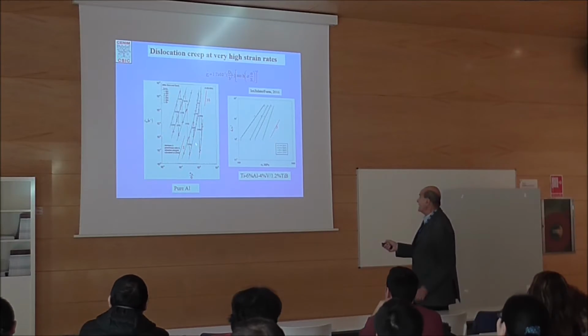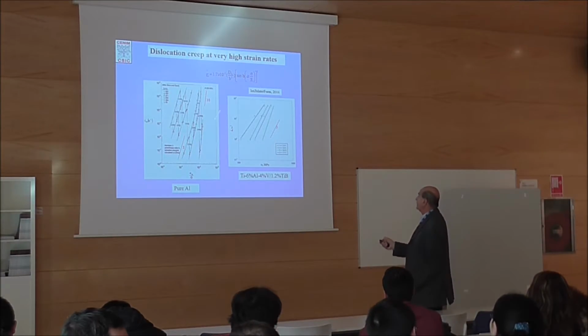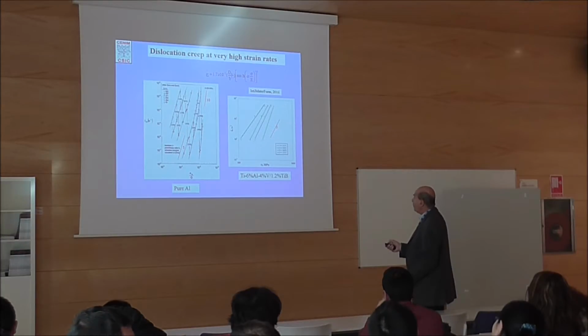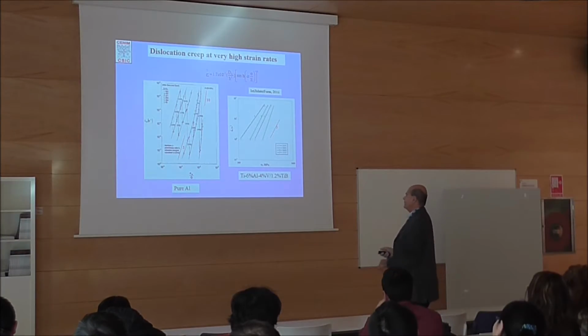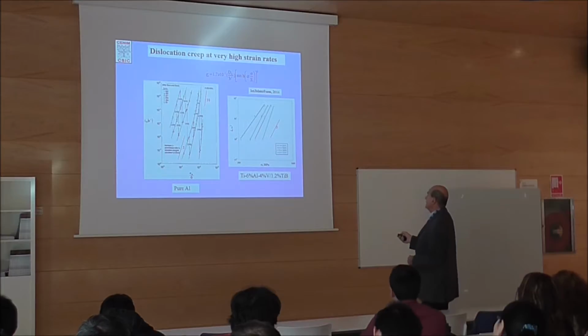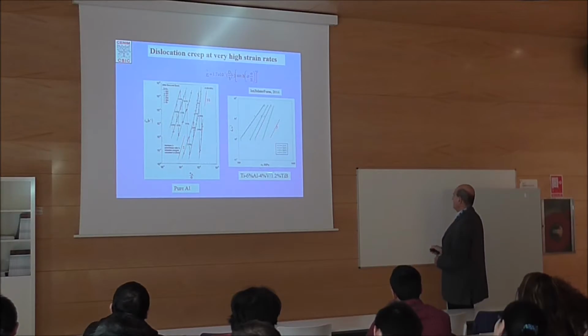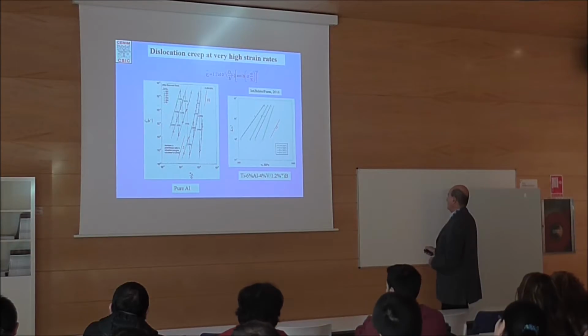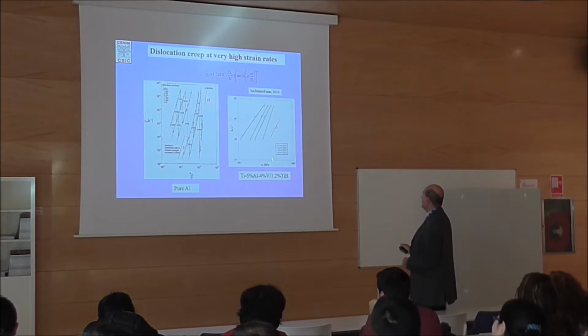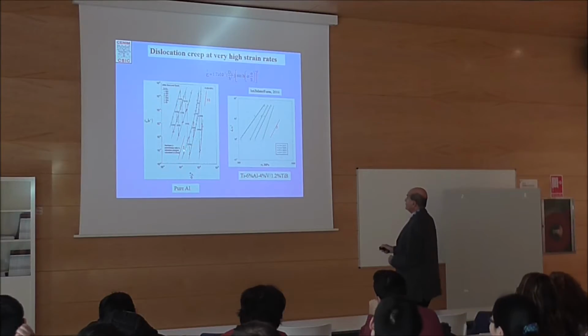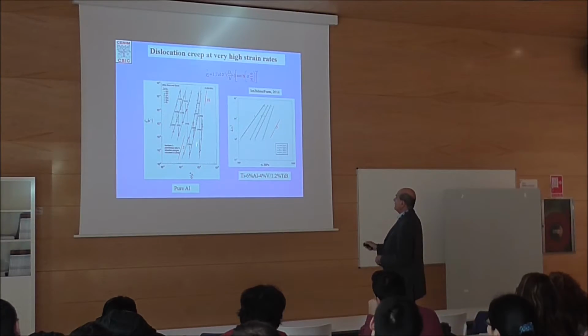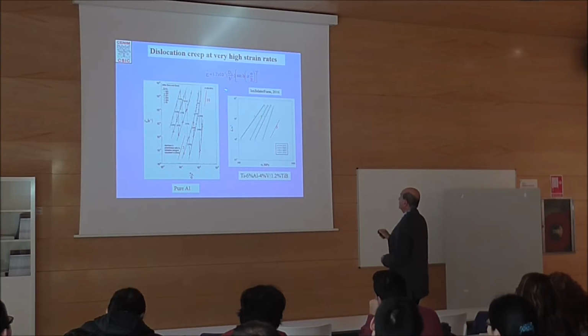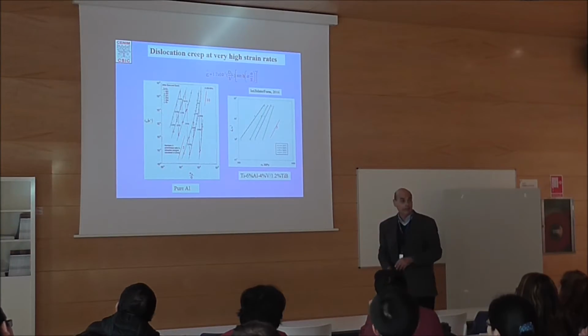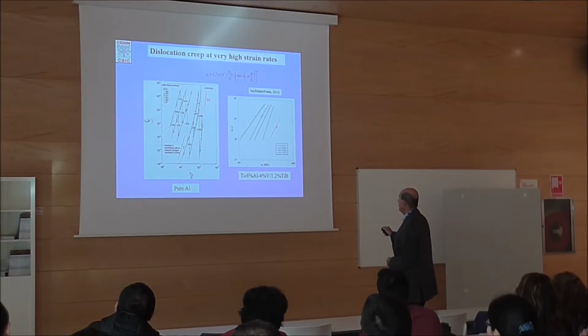You have a sine here that goes up according to this equation, but more important, this is another fundamental thing. There are in some cases, for instance, this is titanium 6-4 with 1.2% titanium borides. You don't have this hyperbolic sine branch. We have more or less a constant power law, because if you forget, this is a power law equation. But look what is going on here.